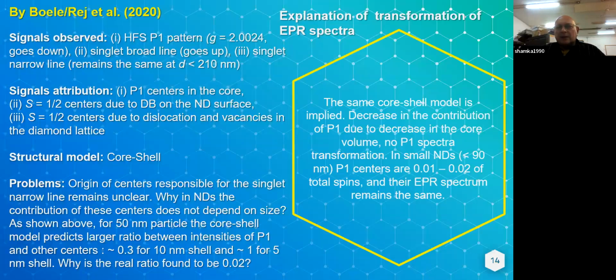Let's go further to the fourth group. The explanation is the same core shell, but the attribution of these new signals is quite strange. They attributed the third line to dislocations and vacancies in the diamond lattice, which appear due to nanonization. Again, when we start analyzing core shell, we could say that the numbers are against this explanation.